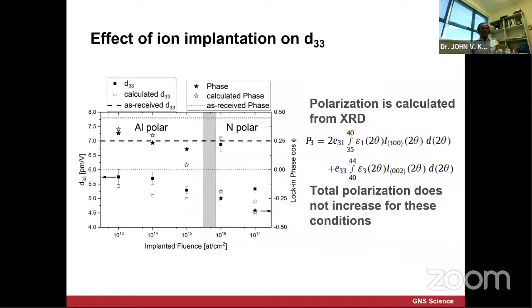We also had an aluminum polar wafer on the surface and a nitrogen polar wafer, and we did a lot of work to understand the d33 on that. You can actually calculate the d33 polarization using XRD data, which not many of you have done, because we always take a simple XRD and say the peak shifts and this means that change. But you can actually extract a lot of new information if you spend a bit more time to understand what is actually happening in the crystal lattice. So theoretically you can calculate d33 from the XRD data, and then experimentally we determine it with piezoelectric force microscopy, which is proportional to the polarization along the C-axis.